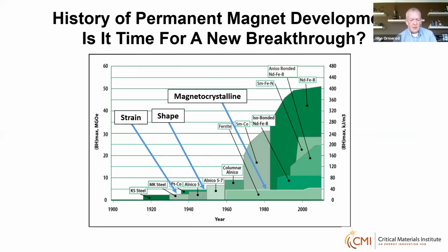What you can see in this chart is the dramatic improvement in magnetic performance of these materials, beginning with the magnet steels in the early part of the 20th century. And in this case, the coercivity in these materials was determined by some strain-induced mechanism. We then got an improvement in coercivity and ultimately energy product when we moved to the Alnico type materials. And the coercivity in these alloys was developed through shape anisotropy. And eventually we moved to the hard ferrites and ultimately the rare earth permanent magnets, where high coercivities and ultimately energy products was achieved through a strong magnetocrystalline anisotropy.